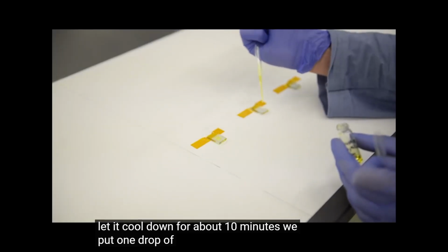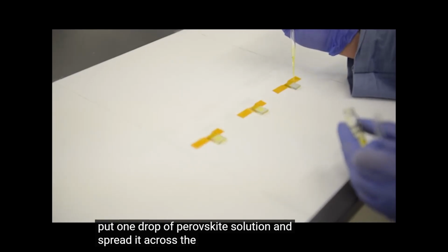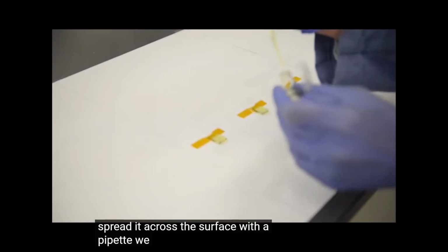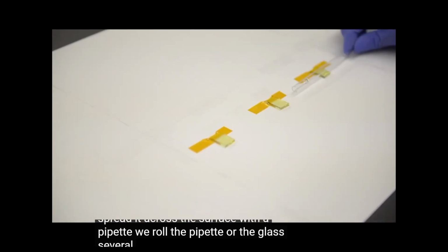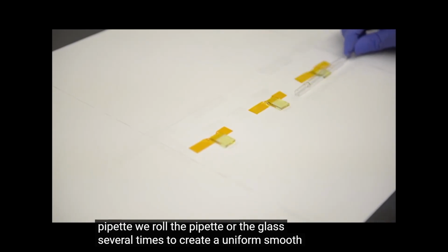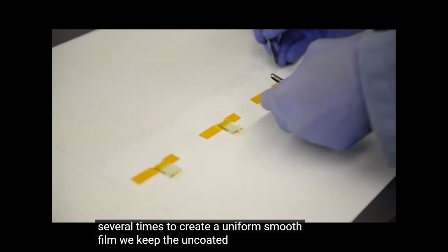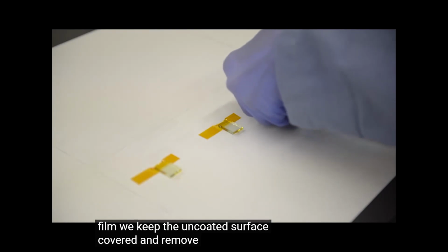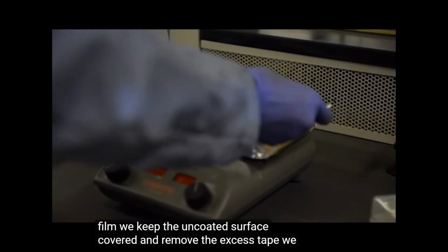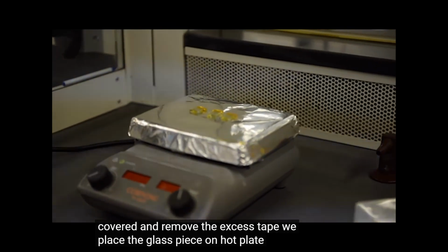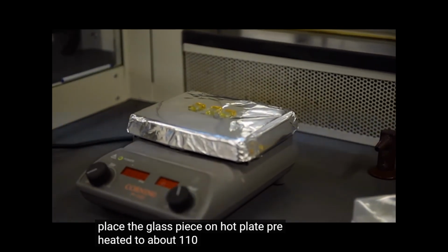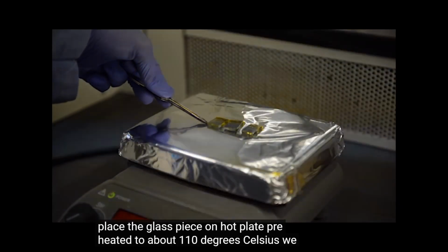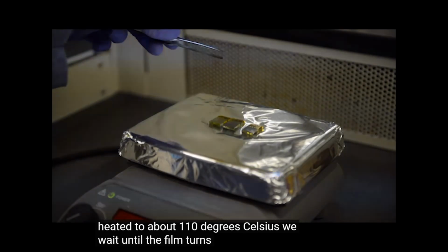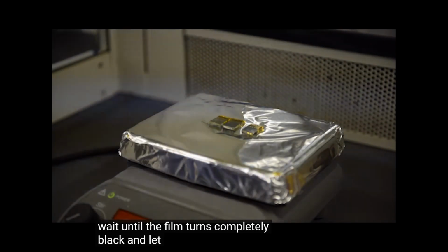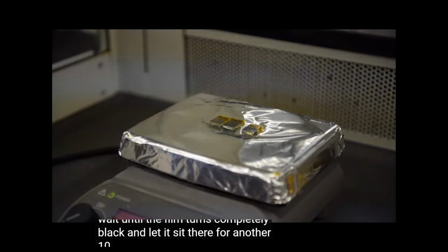We put one drop of perovskite solution and spread it across the surface with a pipette. We roll the pipette over the glass several times to create a uniform, smooth film. We keep the uncoated surface covered and remove the excess tape. We place the glass piece on a hot plate preheated to about 110 degrees Celsius. We wait until the film turns completely black and let it sit there for another 10 minutes.